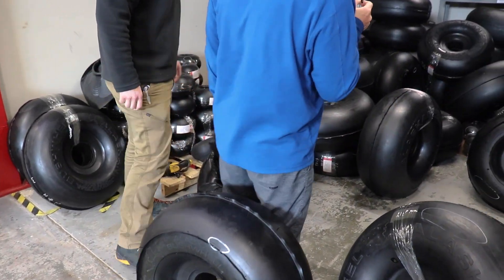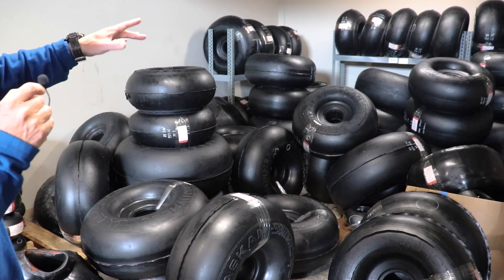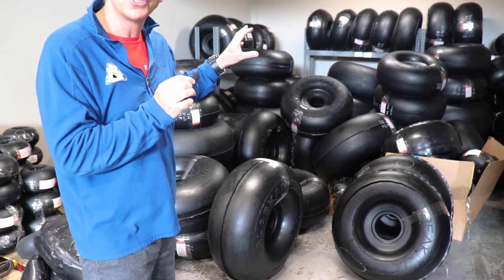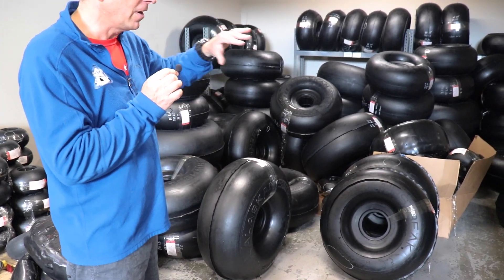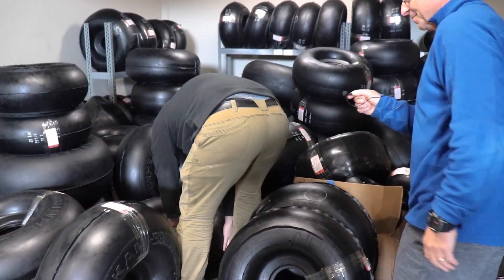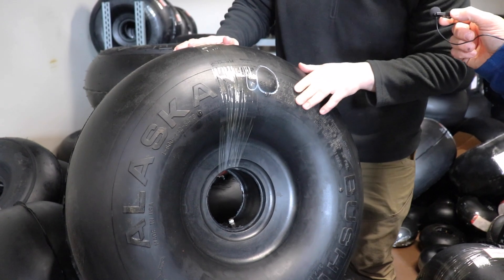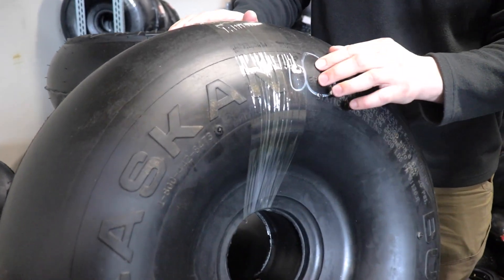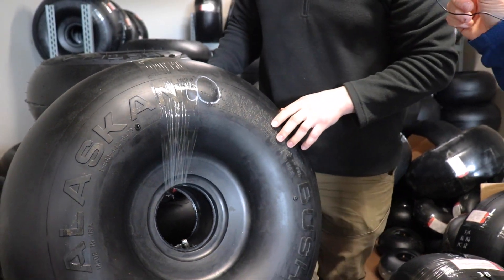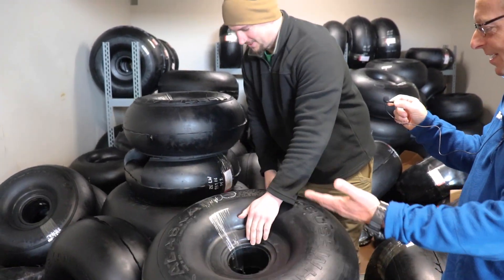Give us some other examples. You can see how many we have here. The reason it's so messy in here is that we've been rummaging through this pile to decide to do this today. Some tires we keep because we're doing research on them, so we're pulling those out for Dan to look at some more. Here's one — this one has a bubble on the sidewall. There was some contamination during the build process, so during the cook it didn't laminate completely on the inside. When you inflate this, it looks like a bubble — I would almost call it a tire zit. So that one we can't sell, obviously.